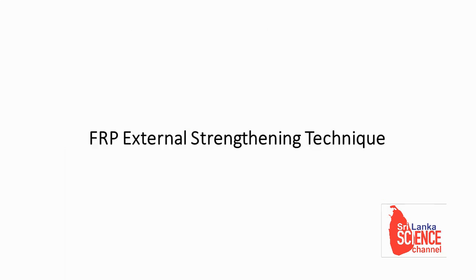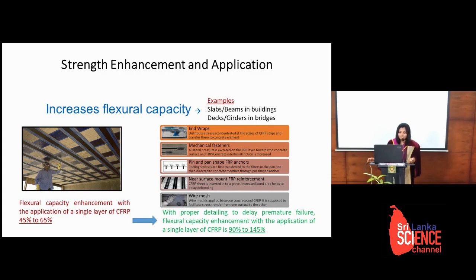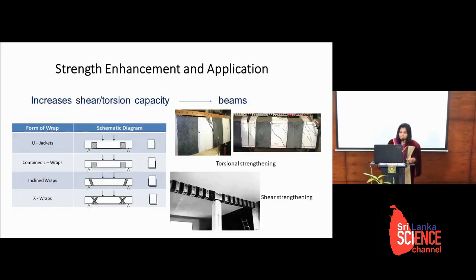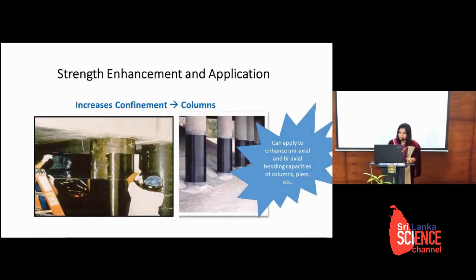Today, my main focus is FRP external strengthening. We can use this technique to enhance the flexural capacity of flexural members in bridges or slabs. If we use a single layer, we can achieve at least 45% strength gain. But with proper detailing, it comes to 90 to 145%. So that means detailing is very important in this technique, because we can save a huge cost in a renovation project. It can also be used for shear enhancement, torsional capacity enhancement, and also confinement and bending capacities in compression members like columns or piers.